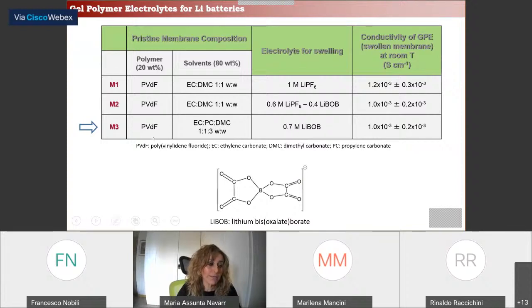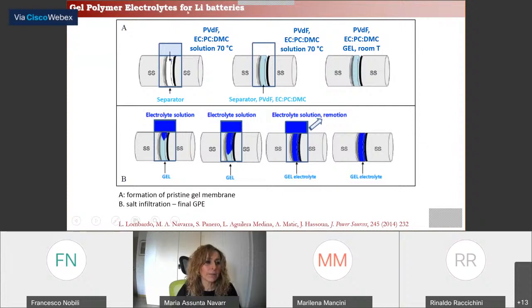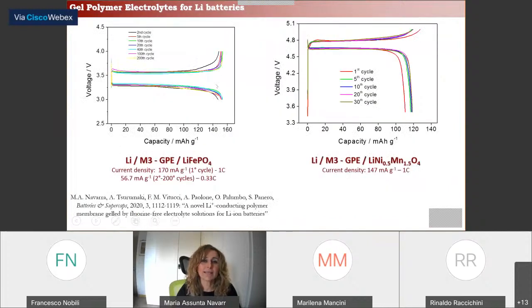That's why in this project we finally proposed a polymer membrane based on a PVDF polymer matrix swollen by a solution containing a mixture of carbonates and a lithium bisoxalate borate salt. During the project, we also developed a way to prepare in situ during the cell assembly the gel polymer electrolyte, and this particular gel polymer electrolyte composition was successfully tested in lithium metal batteries with both the conventional lithium iron phosphate cathode and high voltage lithium nickel manganese oxide.